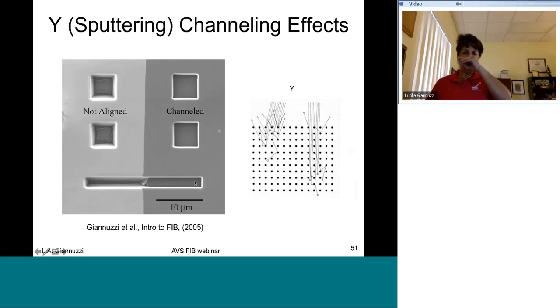The sputtering is also a channeling artifact, as I showed earlier. So if you're in a channel direction, you're not going to sputter as deep as you are in a non-aligned or non-channel direction, just because the interactions are going to happen a lot deeper in a channel direction, and so you're going to get less sputtered particles coming out of the surface.